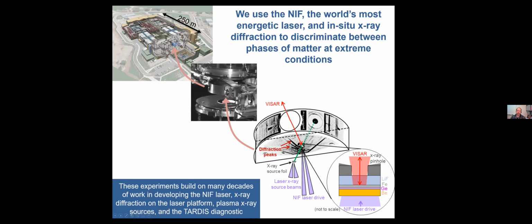where our sample package is put on the front face of that diffraction diagnostic, which again is basically a shielded image plate box, where our sample is composed of a stack of samples. So again, the idea is we use 16 beams of the NIF laser to drive a shock wave, where we use beryllium as an ablator. It's a low Z, very efficient ablator, doesn't generate high energy X-rays. We then use germanium to shield the X-rays from our iron sample, and then a lithium fluoride window so that we can diagnose the pressure states while maintaining the peak pressure.